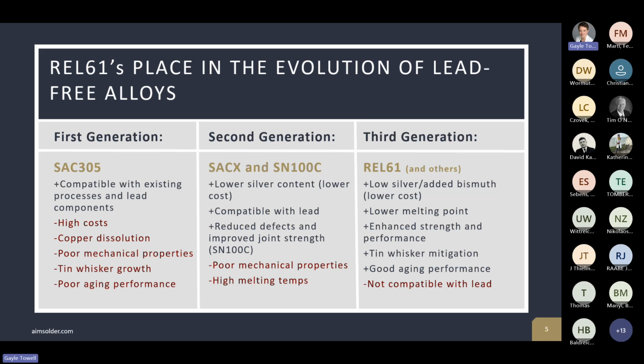Third generation alloys have now come on the scene. REL61 falls into that category. REL61 is a low silver alloy, so it tends to be lower in cost than SAC305. It does have some bismuth added, and the small percentage of bismuth tends to improve a lot of the mechanical properties. It also slightly lowers the melting point and improves the aging performance quite a bit. The only drawback being that bismuth containing alloys tend to not be compatible with lead. If there's still lead in the process, bismuth can combine with lead to form a very low melting eutectic, which can cause some structural issues with a joint.